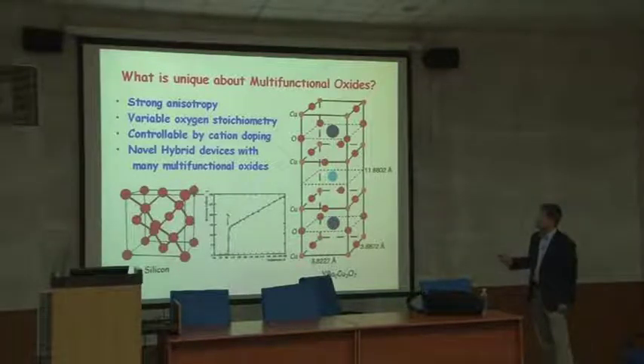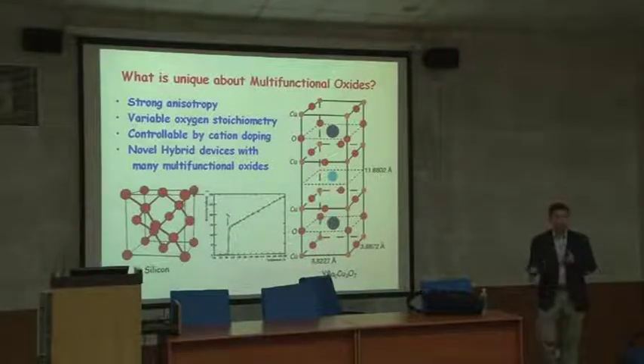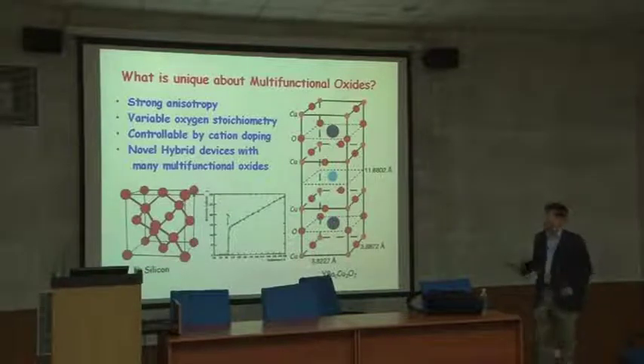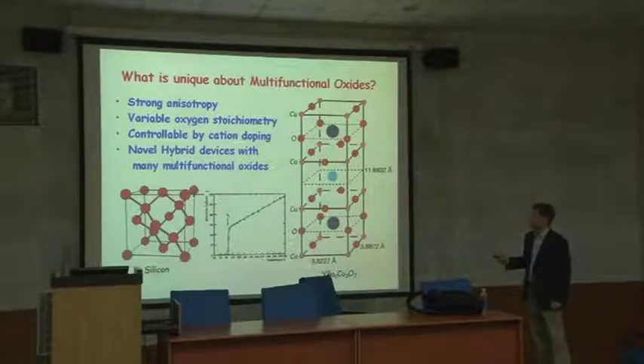And oxygen, as I said, can go in and out, so oxygen stoichiometry is very important in this system as well. And also cation doping, especially A-site cation doping, causes a metal-insulator transition. For example, the first superconductor discovered, the lanthanum barium copper oxide system, without any doping of the barium is itself an antiferromagnetic insulator. But when you add the dopant, it becomes metallic and superconducting. So cation doping is also very important.